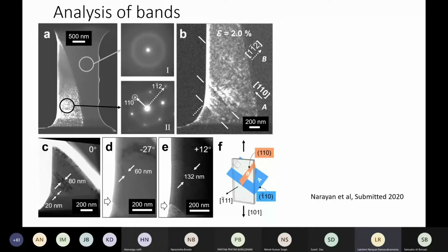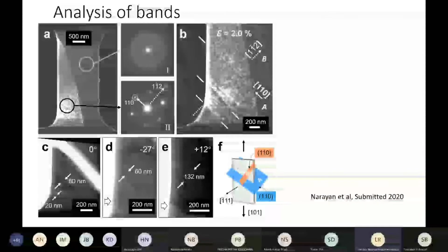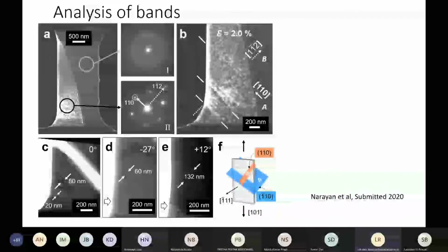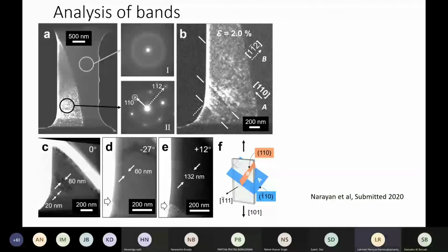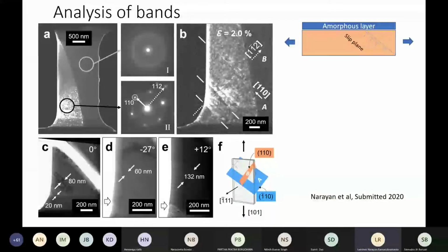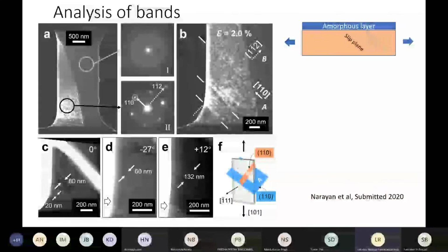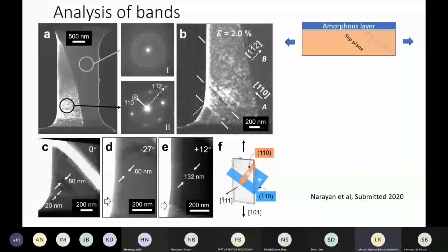So if we analyze it, what really happened is we did another test to observe what these bands are. These dark bands are nothing but slip over different dislocation slip planes. And these different dislocation slip planes were identified as 110 and bar 110. These are just notations for different crystallographic planes in the material. Now, if you want to understand the process, look at an amorphous layer that has been kept next to the crystalline layer. Let us say your corner is nucleating dislocation slip, and dislocations start propagating over this particular slip plane, and as they hit the interface they are not able to go through it, so a shear step is not able to form.